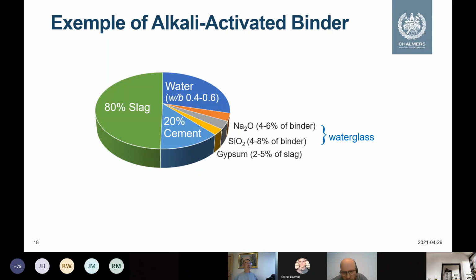So after our research, we suggest this proportion for the alkali-activated binder: about 80% slag, 20% cement, and then about 4 to 6% sodium oxide and 4 to 8% silica. This is water glass, so we can adjust the water glass at this level. Then we can use a water binder ratio of about 0.4 to 0.6 so far. If we use this proportion, we can dramatically decrease the carbon footprint of concrete production, and also keep a similar strength development.